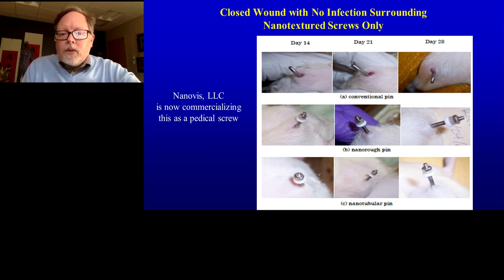The middle row and the bottom row are two examples of nanotextured surfaces. One was that nanotubular surface geometry that we created using anodization. If we change the process a little bit, we get what's called nanorough, not nanotubes, but just hemispheres of nanoscale features. Either type of nanoscale feature we created, you can see the wound closed. So the skin grew onto the screw after 14, 21, and 28 days. This again kept bacteria out. It reduced inflammation, and it allowed the pin to grow into bone.